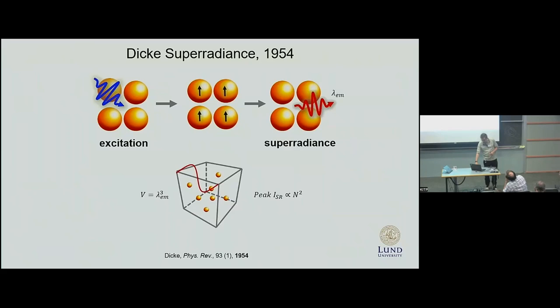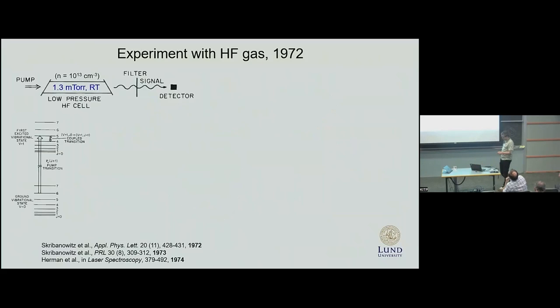The first experiment claiming this effect appeared in 1972. It was on hydrogen fluoride gas, in a low pressure cell. How low? A number density of 10 to the 13 per cubic centimeter, roughly 10 molecules of hydrogen fluoride per cubic micrometer of space. You can imagine the molecules are really far apart.